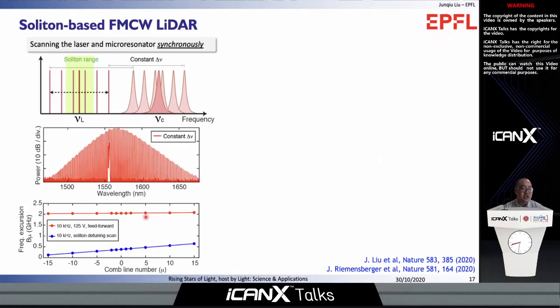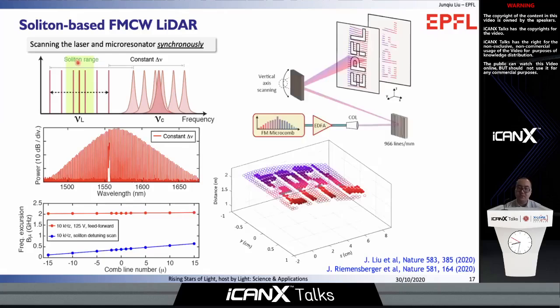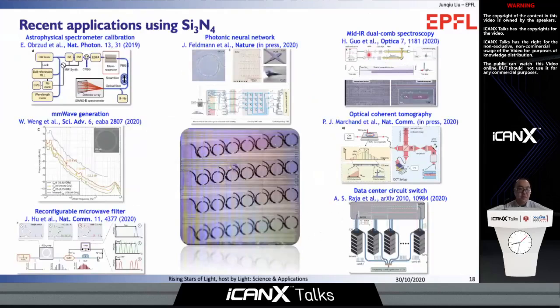Here we can achieve a frequency excursion of 2 GHz, which is significantly larger than the soliton existence range. We also perform a proof-of-concept ranging experiment using our soliton-based massively parallel LIDAR. We image the logo of EPFL, and we can achieve 5 centimeter level resolution.